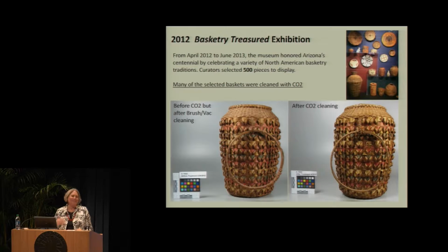So I believe that we were having these initial good results because we were mostly trying to remove desert dry particulates. Our basketry surfaces did have a structural stability, and many actually have a cuticle or a bark layer present. Our basketry and textile fibers were not really thermally conductive, so we weren't going to see the things that metals and glass often do. And it really did appear through testing that our surfaces were able to withstand the force of the jet.